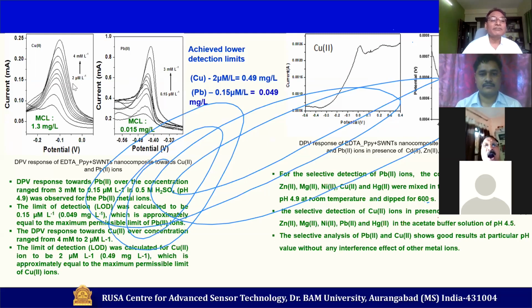You can see copper, we varied the concentration right from 2 micromolar to 4 millimolar, and you can see the substantial difference, discrimination in various peaks as well. And same thing is true with lead as well. Now, as far as the MCL level is concerned, whenever we are talking about any sensor, you need to see what is the low detection limit, and whether it reaches the standard level which we were talking about, right? So this MCL, US EPA talks about this MCL level. For copper, the MCL level is 1.3, and we could reach 0.49. It means we went well ahead of the MCL. So this is one of the successes.